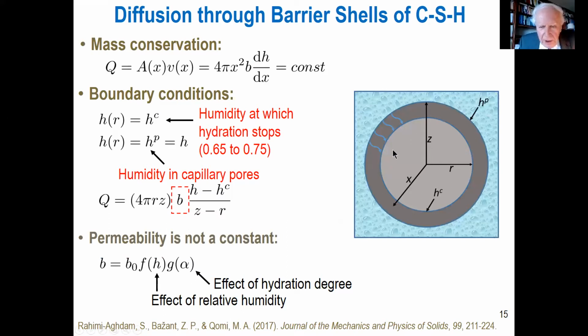So here is the model, and here is the grain, the shell, and permeating water molecules inside, balanced by ions going out. That's easily calculated. A mass conservation equation must be written, with the gradient of the humidity or equivalent humidity throughout. Actually, pressures can be translated to humidity because it's uniquely related. Then boundary conditions: we have to calculate humidity in capillary pores, that's written here. Permeability is not constant, it decreases with hydration because the structure is getting more compact with hydration degree. The hydration degree is alpha, that's included here. It depends on humidity. I will mention later that as humidity goes down from 100% to 50%, it drops about 50 times. So that's why hydration is so terribly slow.